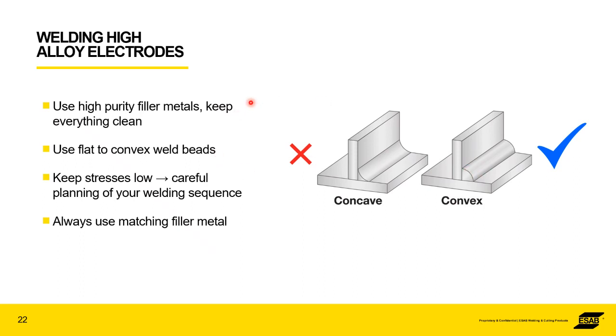And so the ways to help are to make sure everything's clean. Obviously, it's a stainless steel. The higher the alloy, the more problems there are, so keep everything clean. The bead shape is important. Thermal stresses, so welding sequence is important. Don't put all the heat on one side, for example, or it will crack. And the filler metal choice is an obvious one.